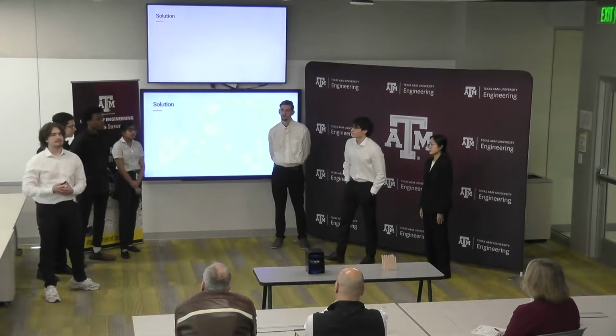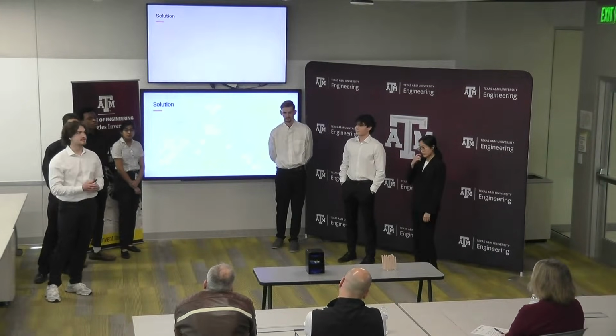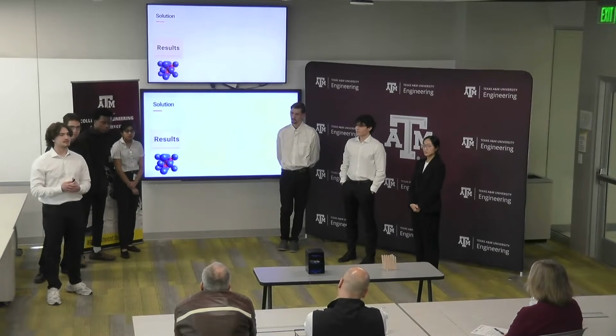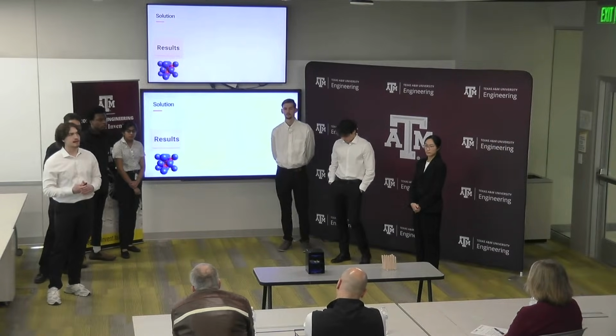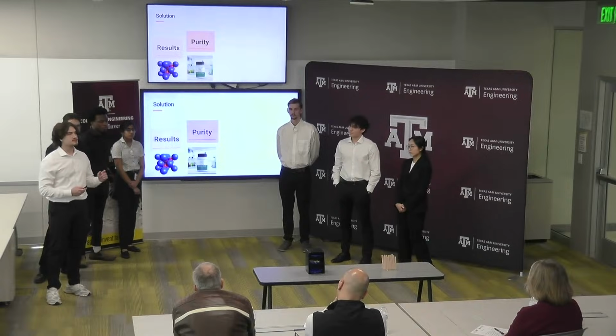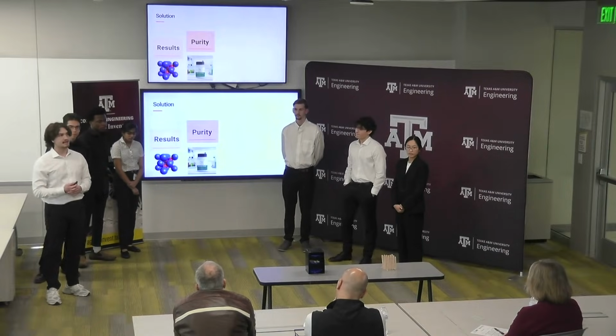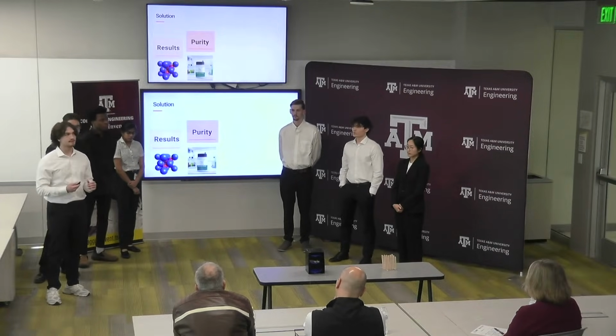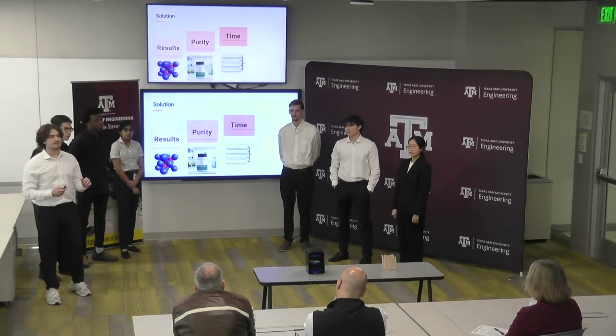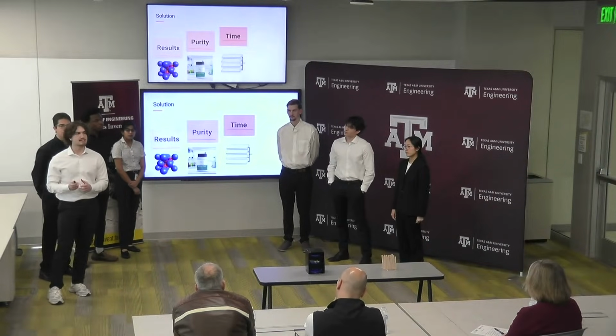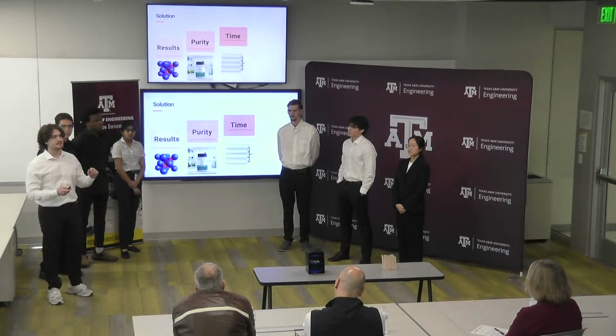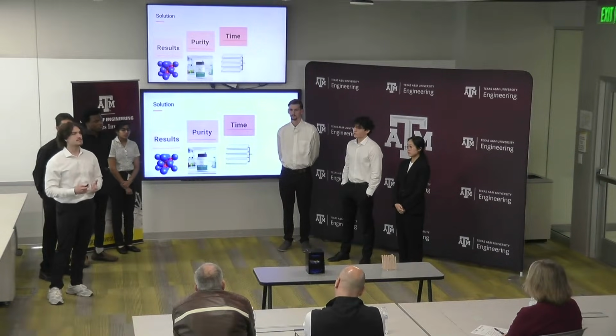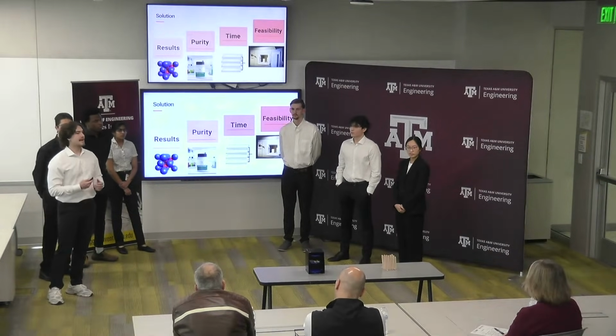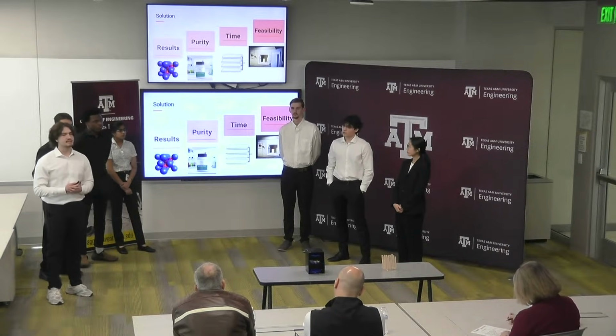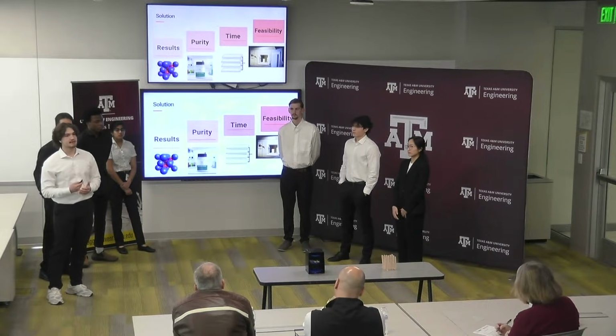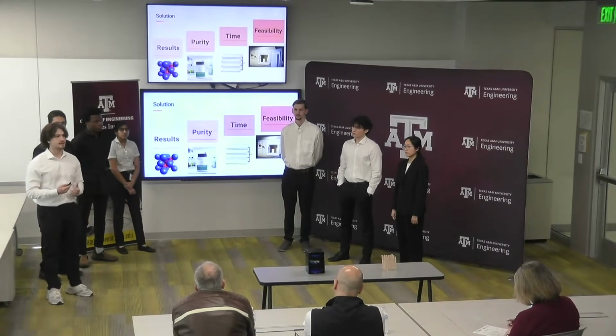And now we have come full circle from our problem to our solution. We will achieve the results we want of increasing domestic production of Americium through making sure that our maximum surface area crucible design gets the 95% purity or greater, through decreasing the time from the old chemical process and drying process taking almost 5 to 6 hours and decreasing that to 2 to 3 hours in our new furnace, which is reducing the time by half, and feasibility. These can be implemented into the hot cells instead of the glove boxes, making it more safe and efficient for the workers and operators.